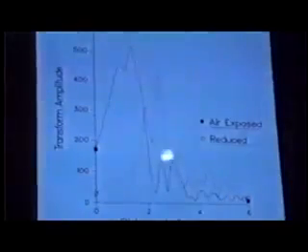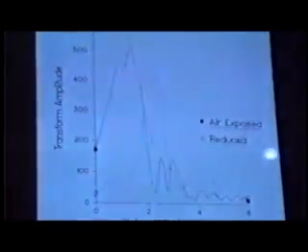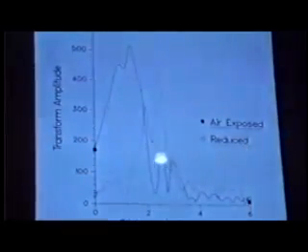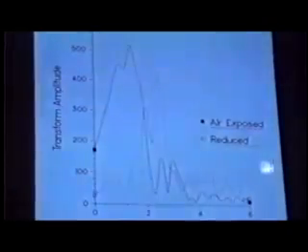We are seeing, as in the fully reduced case for the highly dispersed catalyst, the catalyst which was in situ pre-treated with hydrogen prior to EXAFS measurement, there is a side lobe at distances less than 2 angstrom which may be indicative of ruthenium-oxygen coordination.